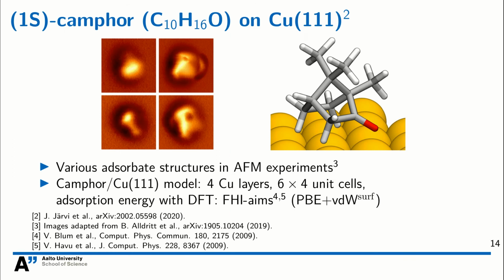Next, I'll show one application of BOSS. Here we have studied the adsorption of a camphor molecule on a copper 111 surface. This material has also been studied experimentally with atomic force microscopy, and the images show various different adsorbate structures. Now we apply BOSS to identify the stable structures. Our model has 4 atomic layers of copper, 6x4 unit cells, and we calculate the adsorption energy with DFT using the FHI-aims software.